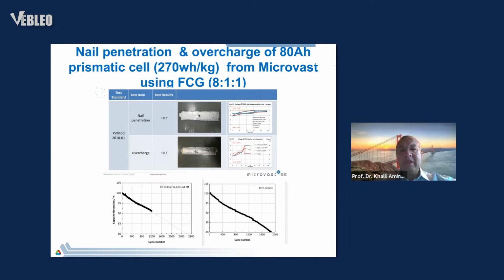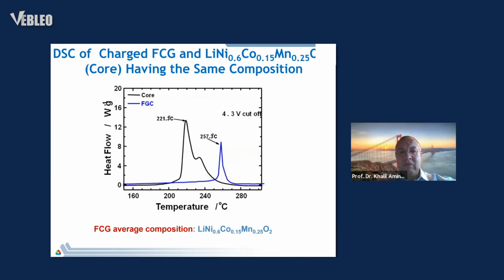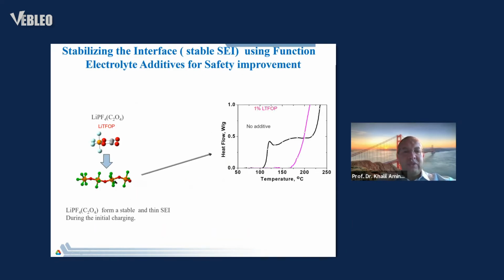Now, the reason why this material is safe is because the cathode is safe. You can see when we charge the cathode, comparing to the NMC 811, for instance, NMC 811 has an early reaction and the overall heat is very significant. However, the FCG has much more resistance to reactivity. You have to heat up to a higher temperature. The activation energy is very high, and the overall heat is very small. So it generates very small heat, even at high temperature.